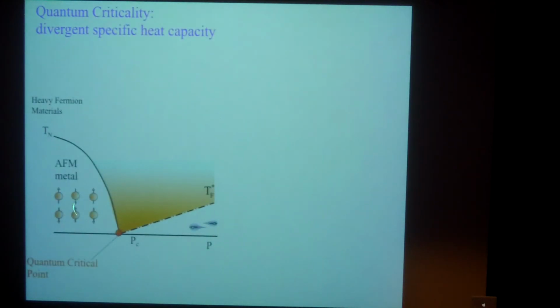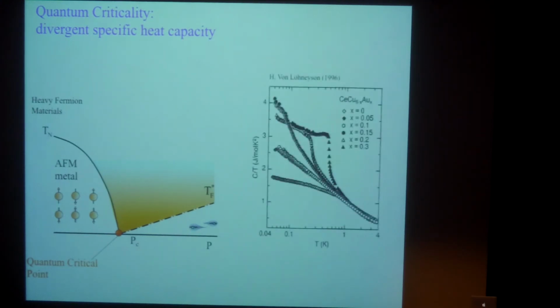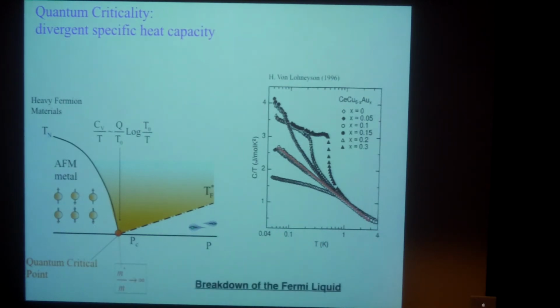Okay? Here is a cartoon of quantum criticality. As you tune some parameters, such as pressure, you go from antiferromagnetism to a Fermi liquid. Here is a real system, cerium copper 6 gold, where the gold tunes negative pressure, drives you actually from the metal into the antiferromagnet. You can see the antiferromagnetic transition. And notice that C over T has a logarithmic behavior at the transition. This logarithmic behavior is a sign of the breakdown of Fermi liquid behavior. And many systems exhibit this behavior with a characteristic temperature scale T0 and a Q here, which is typically of order half log 2. And this tells us that the mass has gone to infinity and a breakdown of Fermi liquid.